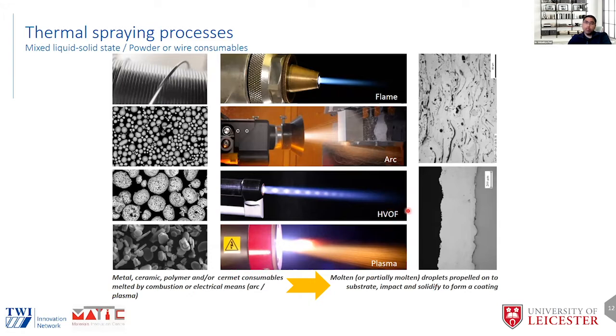You can have high velocity oxy-fuel. This is primarily used for carbides and stellite type materials in the powder form. The particle velocity is supersonic, and this produces quite a dense coating. We also have plasma. In the case of plasma, we tend to use ceramic materials or materials that have very high melting point, and plasma generally creates 10,000 Kelvin or so temperature, which melts all the materials that we have used so far. So we tend to get different coating morphologies depending on the consumable and the type of power source we used.